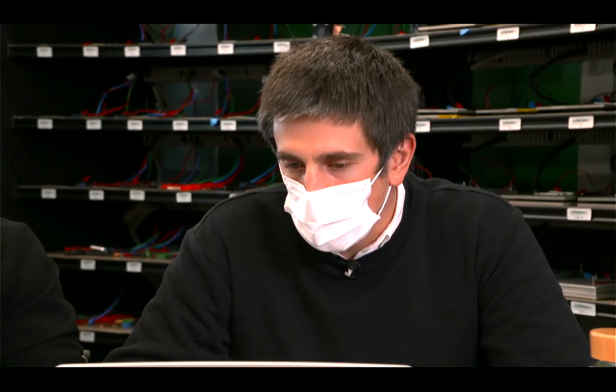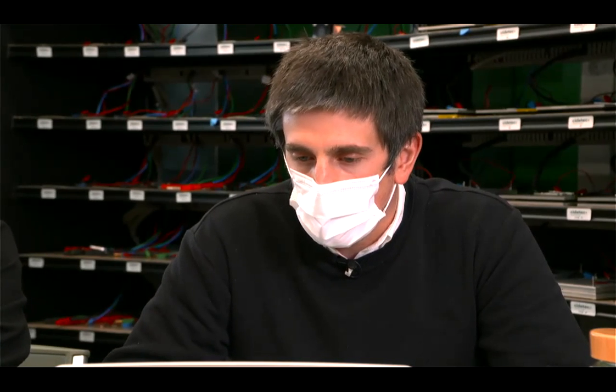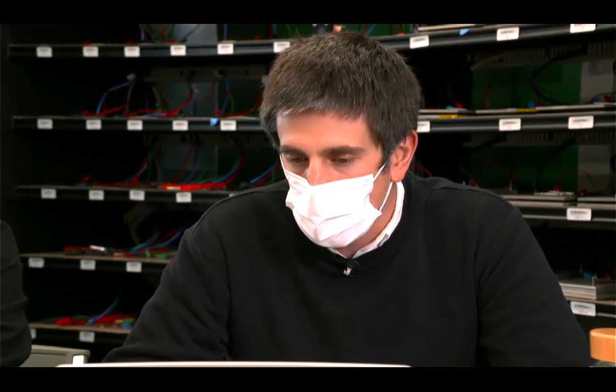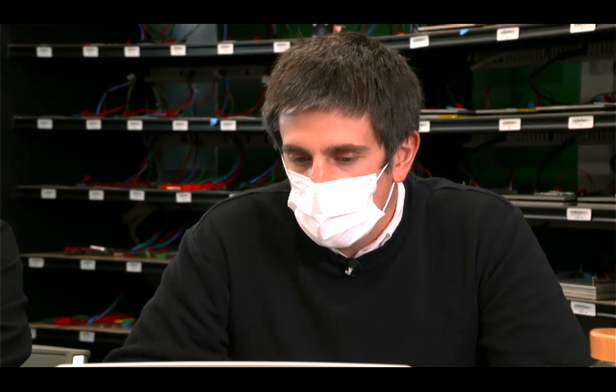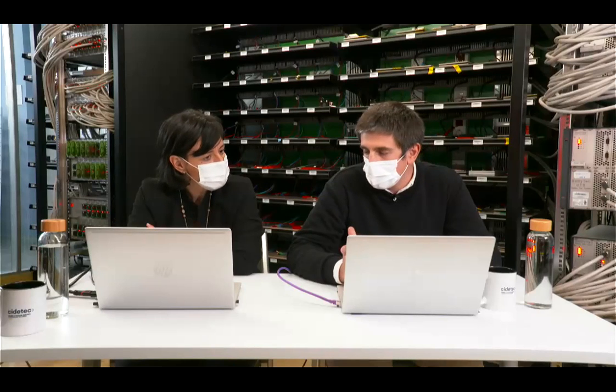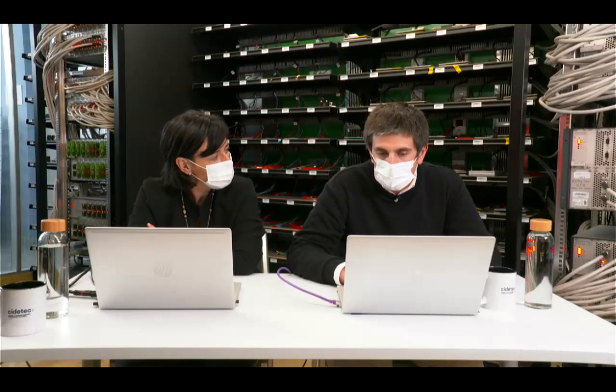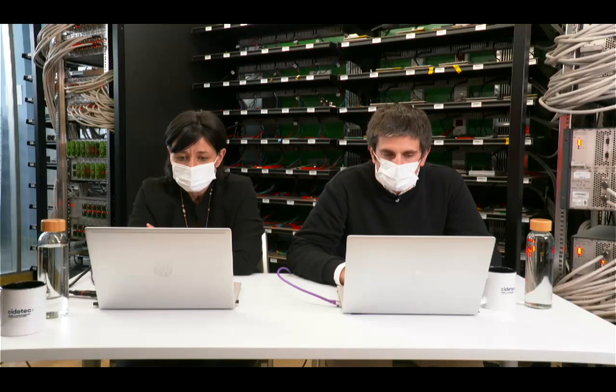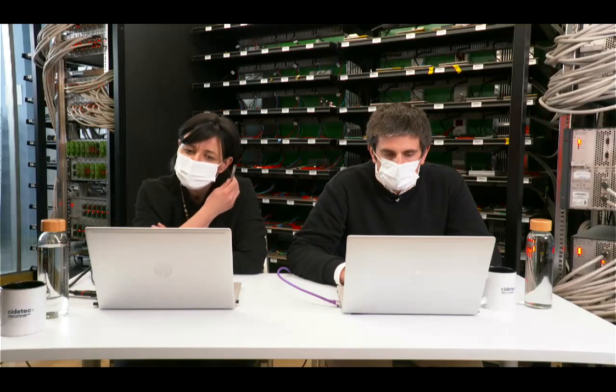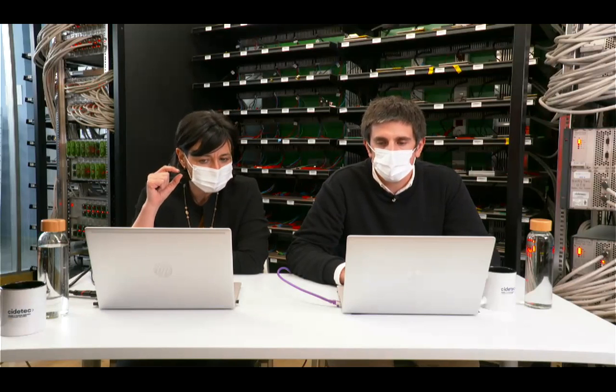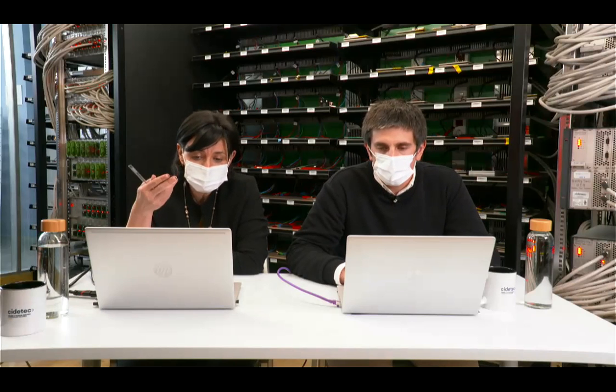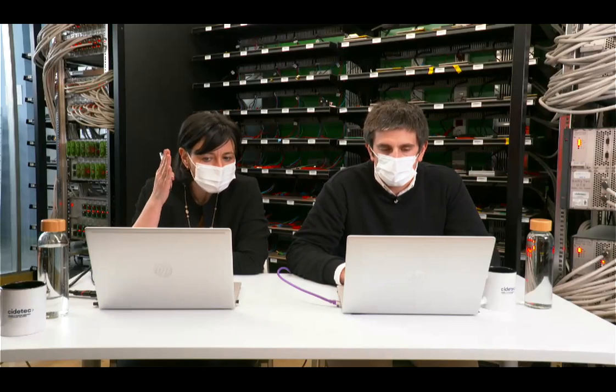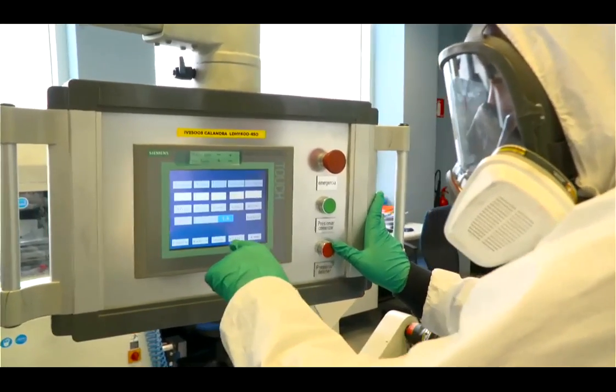But you have to take into account, if you are thinking about power applications, maybe these parameters should be changed. So the density values that, for example, we said about the NMC, that is 3.2, depend on the application of the final battery. So we cannot say what is better. It depends on the requirements that you want to target. Yeah, this is what we were discussing before. You need to keep at least a minimum porosity, because the electrolyte has to wet the electrode. So there is a minimum value that you need to keep.